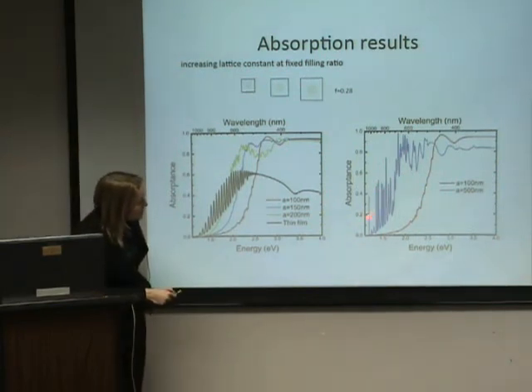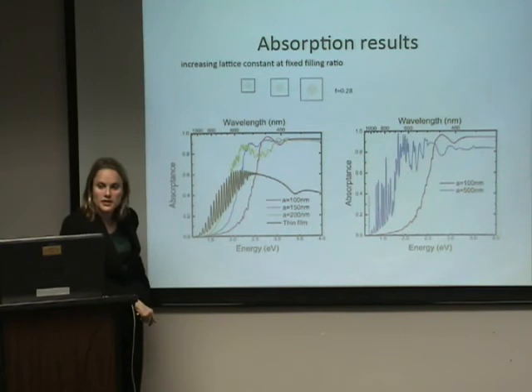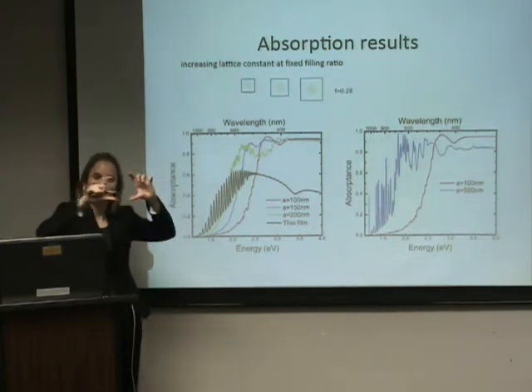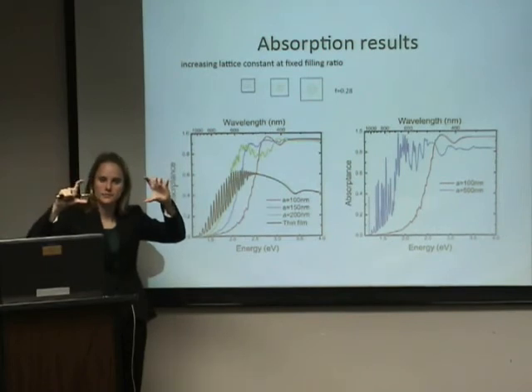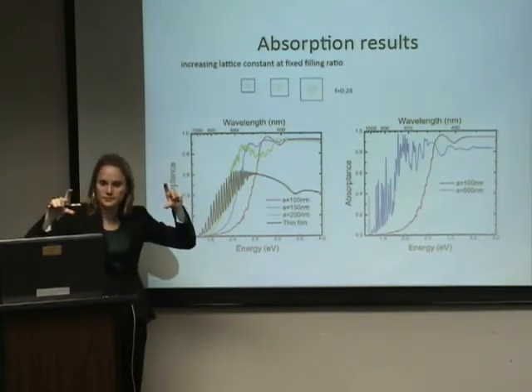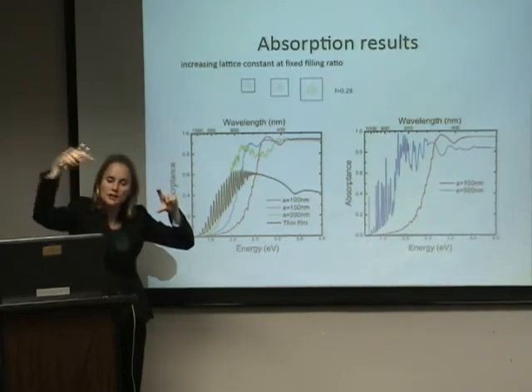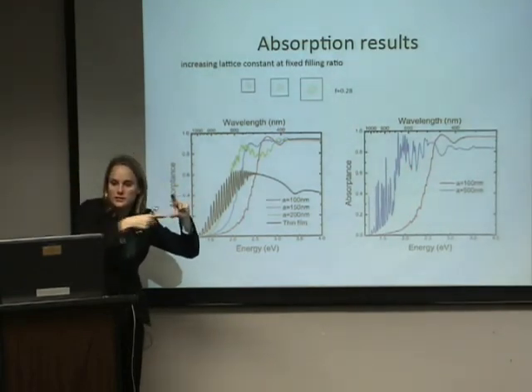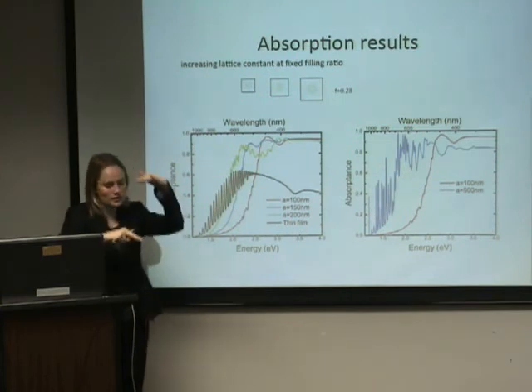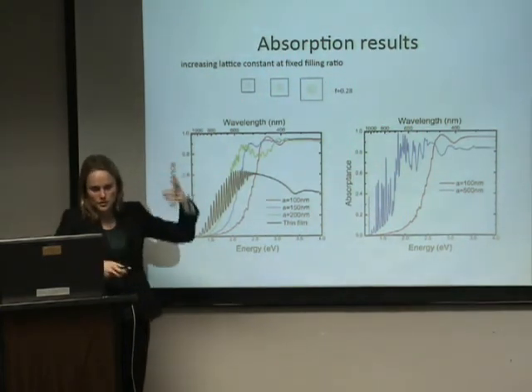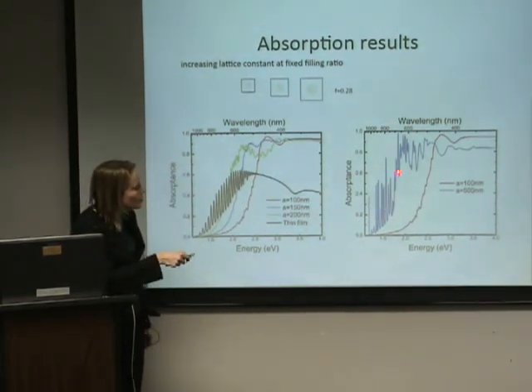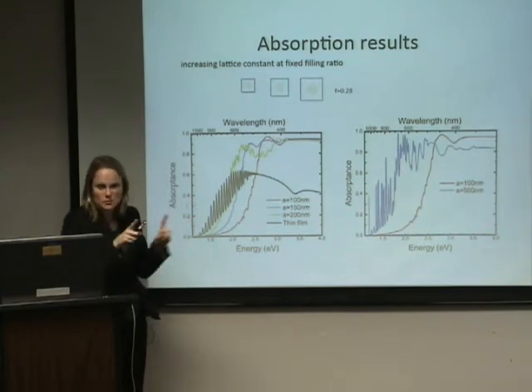So these come from what are called guided modes of the nanowire structure. They're localized to the film, and if you come in off angle, then they're actually propagating in the film. And as you make it longer and longer, the density of modes increases, and so you get more narrowly spaced peaks. Then they start to merge, and then it should get smoother.